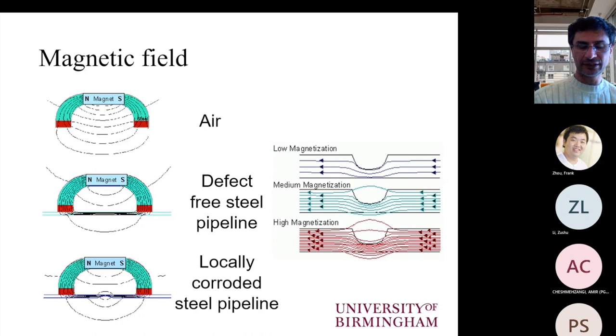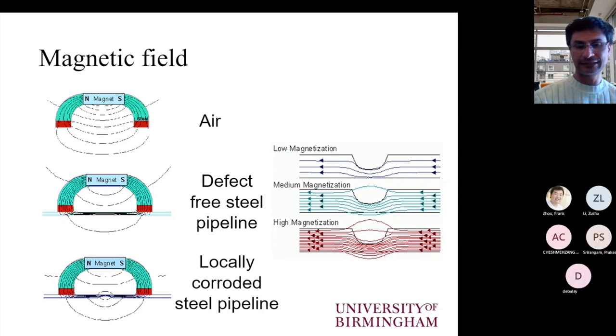In the case where we have corrosion or a crack defect which causes enough leakage to occur, then some of the flux will leak. And of course, that is what we are going to try to detect with our Hall probes or with our coils. Now, very important, however, is to take into account the level of magnetization. So if the level of magnetization is not sufficient, then we may not have leakage occurring at all, which means defects can be missed, or they can be underestimated.